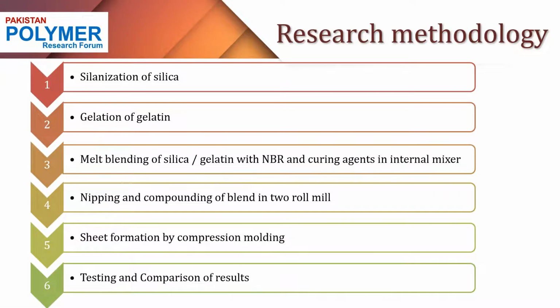The first methodology step was the silanization of silica. As it was the first step, I used silica as a compatibilizer in this elastomeric formulation. As silica is the second most abundantly used filler in elastomers after carbon black, I selected silanized silica as a compatibilizer in this elastomer.